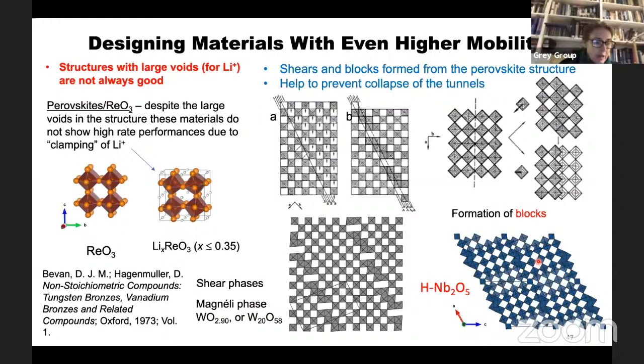Okay, so I want to just end by telling you a little bit about our work on making even faster materials with even faster mobility. And so if you step back and ask the question, how do we do this? Well, we obviously want materials with holes, so that allows the lithium ions to move through. And some of the most holy materials are these so-called rhenium trioxide structures. So they're perovskites, but they're missing the holes in the center. But the trouble is, once you try and put lithium in them, the octahedra rotate and they clamp down the lithium, and so you don't actually get very rapid lithium mobility.